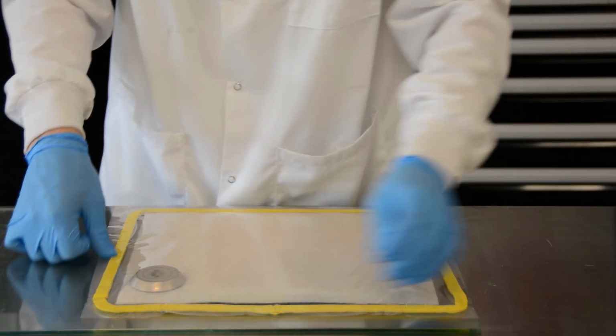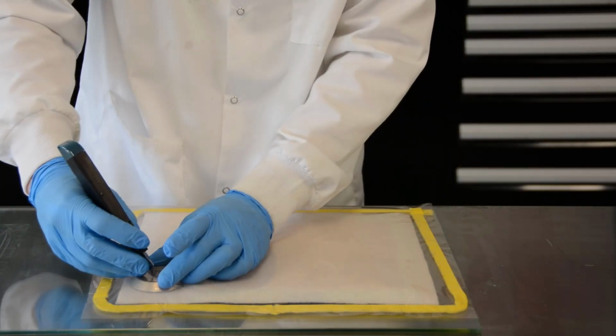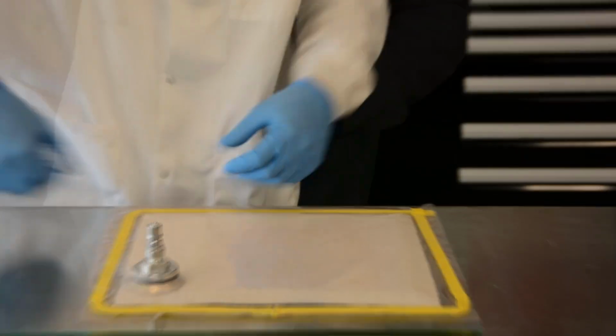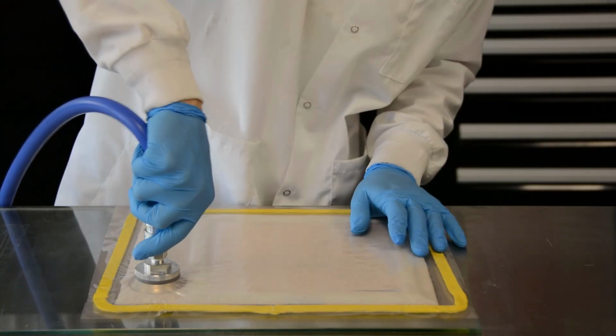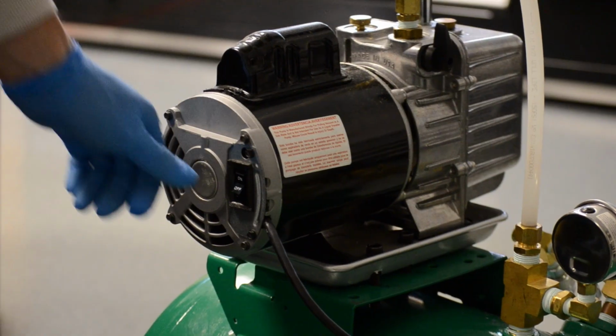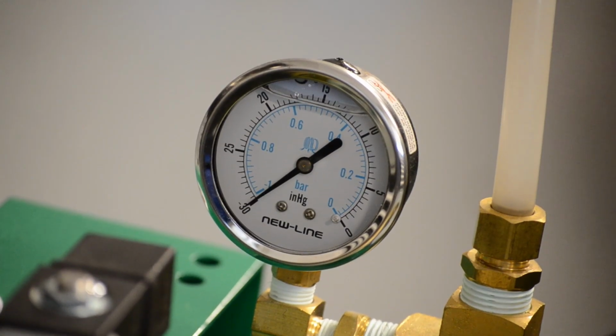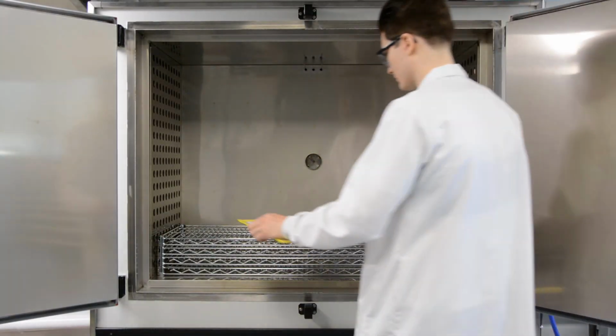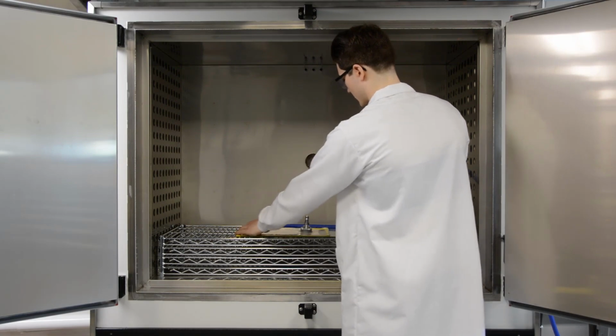The vacuum port and vacuum bag are placed. The vacuum port is installed and a leak test is performed. If leakage is present, air can be introduced into the layup and part quality can suffer. If vacuum pressure is maintained at an acceptable level, the vacuum bag is well sealed and the part is ready to place in an oven or autoclave to cure the resin matrix.